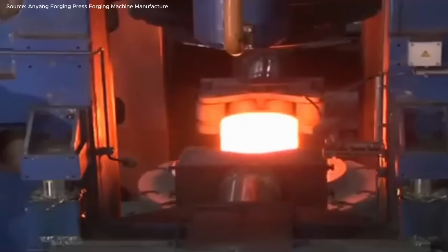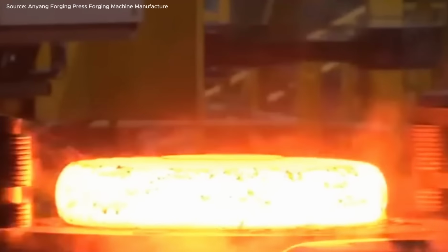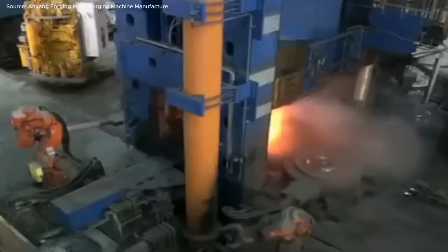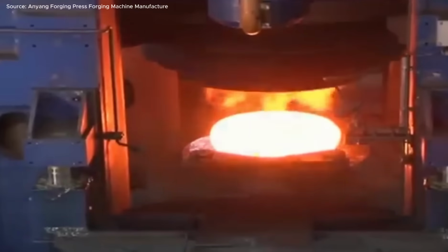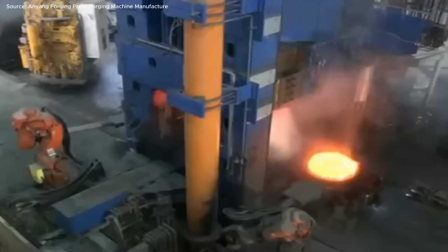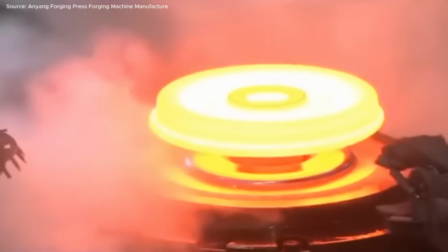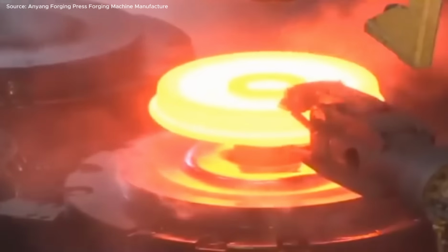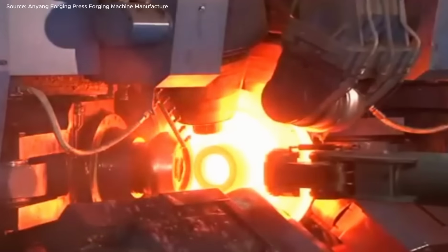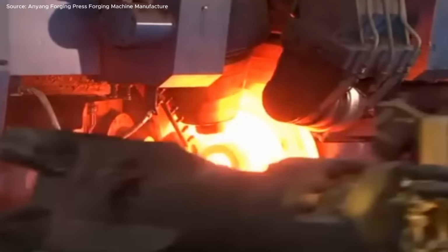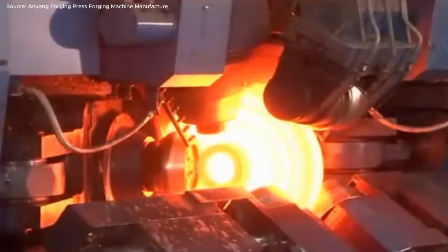The automated train wheel production process represents one of the most advanced examples of industrial forging technology. It begins with the loading manipulator, which precisely positions the heated steel blank into the blanking press. Using an exact centering system, the blank undergoes upsetting under a 9,000-ton press force, forming the initial wheel profile known as the wheel blank. Once the primary shaping is complete, the blank is removed by a transfer manipulator, initiating a fully automated sequence involving 3 industrial robots that handle cooling, lubrication, and CNC-controlled axis adjustment.